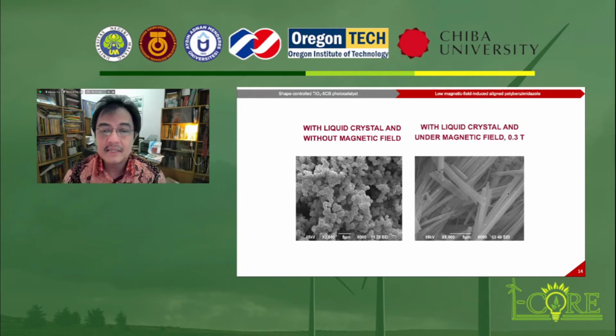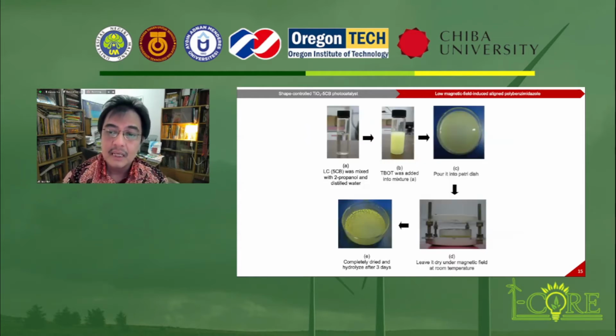This is the synthesis procedure of the well-aligned titania containing liquid crystal. In the first step, 5CB liquid crystal was mixed with 2-propanol and distilled water. Then the TBOT, the source of the titanium dioxide, was added into the mixture and left to dry under magnetic field at room temperature. Then the sample will be completely dried and hydrolyzed after 3 days.